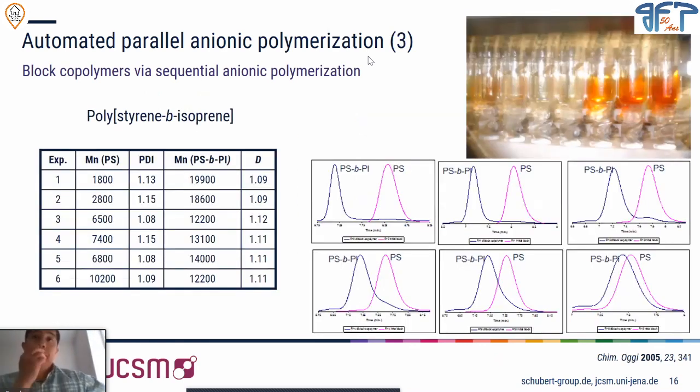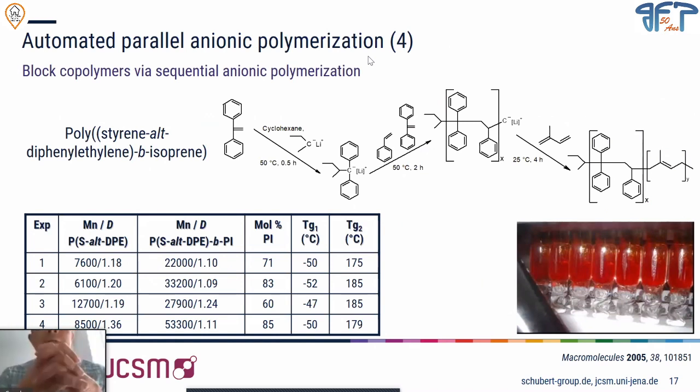But with that, we went back to, let's say, more normal systems, more normal temperatures, and we built up different libraries of block polymers. For instance, here I show you a small library of polystyrene, polyisoprene. All this is mainly done at room temperature. So it's very, very easy chemistry once you have the right conditions of purity of the compounds and the reactors. So you can achieve basically many combinations of these and build a nice library for different purposes, at least some variations in this regard.